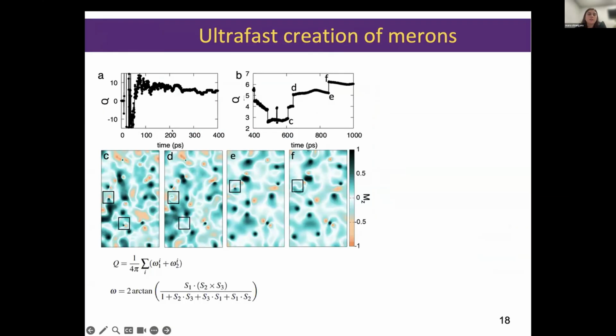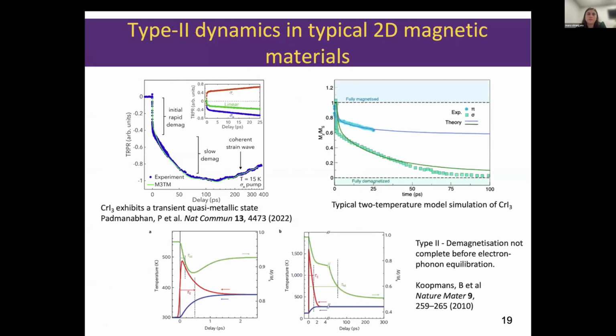And by calculating the topological number, this Q, by triangulating our spin system and calculating this solid angle here, we are able to look at how these annihilation and creation processes evolve over time. So this is one example of a topological charge as a function of time, and we observe these step-like processes which correspond to creation or annihilation of merons, anti-meron structures, vortex, anti-vortex structures in our 2D magnetic system.